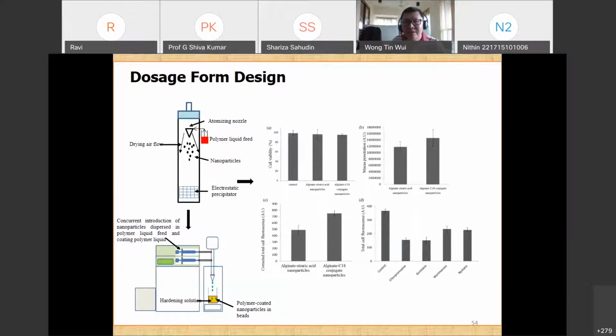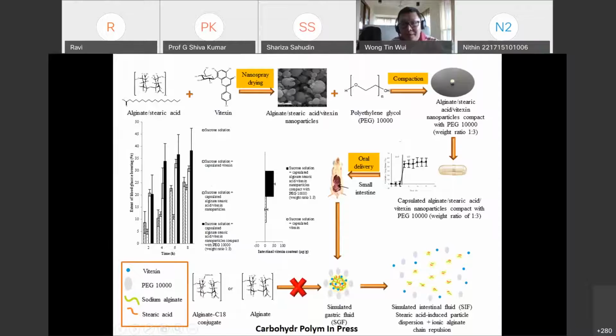You can see in this slide that the nanoparticle we prepared has a very low level of cytotoxicity. It can transport across the mucus barrier and be taken up by the intestinal mucosa prior to entering the bloodstream to exert the anti-diabetic action. The uptake of our nanoparticles by the intestinal mucosa is mediated by the caveolae and clathrin endocytic pathways. And this will be my last slide, but it's our first very successful attempt to formulate the herbal active into the form of nanoparticles for intestinal targeting in diabetes treatment.